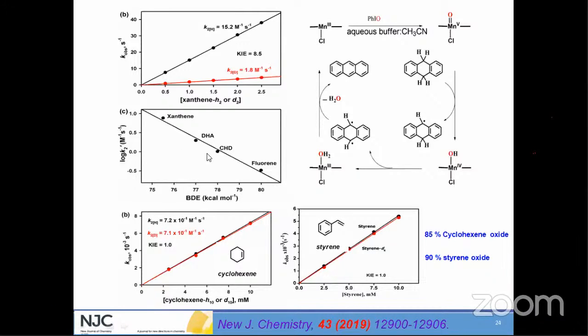When we plotted against that, we got a linear plot, which again gives evidence that the mechanism follows hydrogen atom abstraction as the rate determining step. So based on these evidences, we propose this mechanism. This was the mechanism proposed for this reaction, taking dihydroanthracene as the substrate.